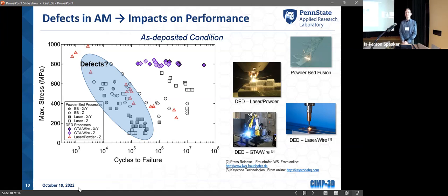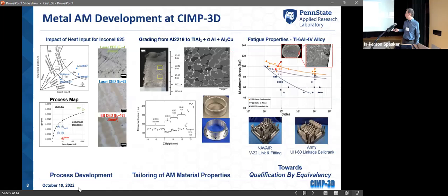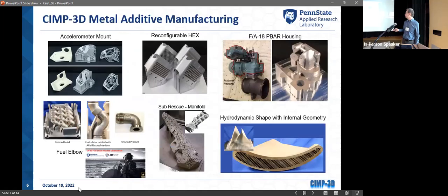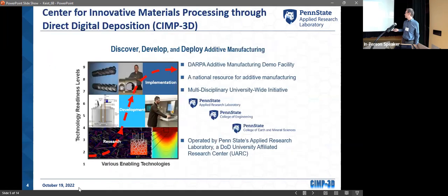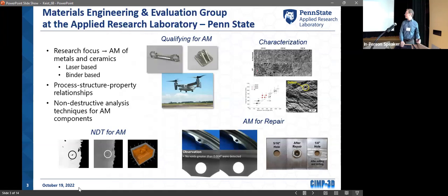Are you developing a different S-N coefficient for these materials, or are you assuming that it's the same behavior? We're assuming the same behavior. For instance, this particular one is an example. We compared ourselves directly to the wrought component, so we had to do the same testing that they had to do to qualify their wrought machined component. We did that for the additive.